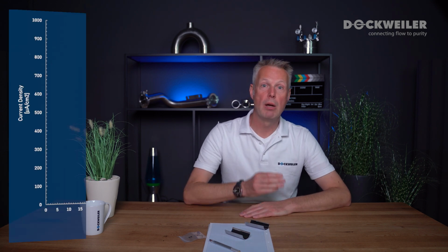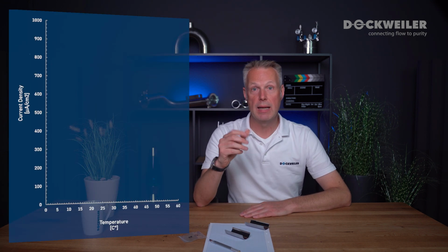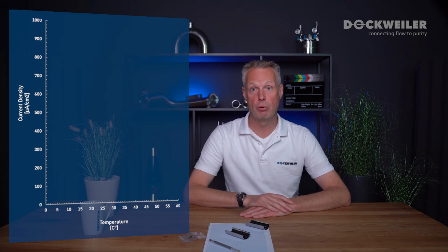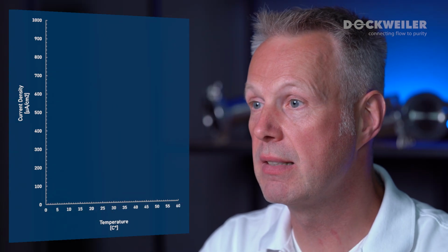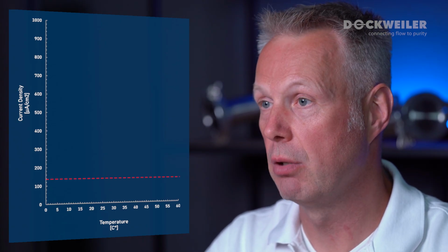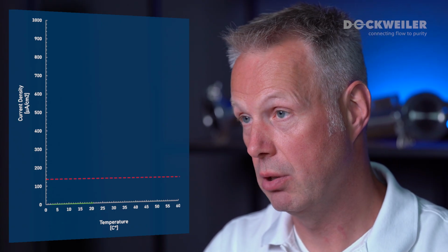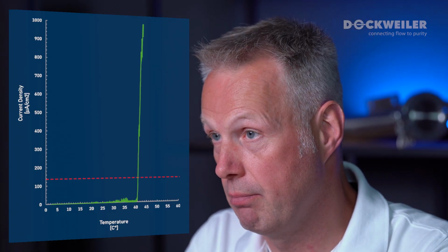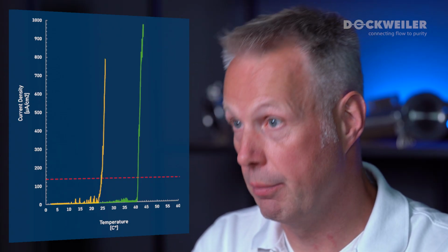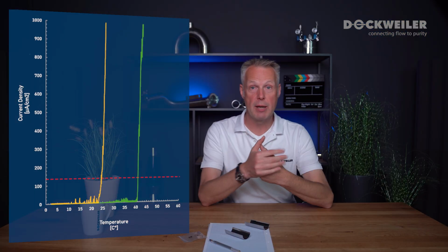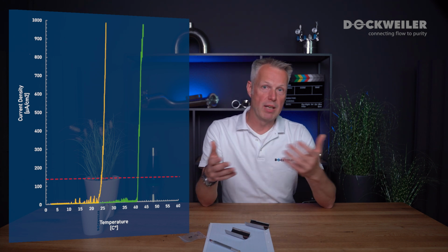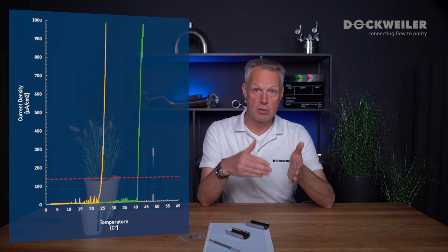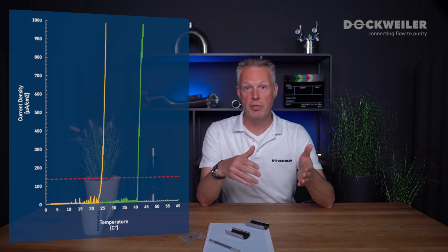So what they basically do is they use a sample that they take from the specimen here, where the steel is the anode, and they have a cathode counter electrode. And what they basically do is they crank up the temperature at a given potential and see at what temperature there is pitting corrosion on the sample. So the earlier the pitting corrosion happens, so the lower the temperature, then that means that the passive layer on the surface is not that well developed.